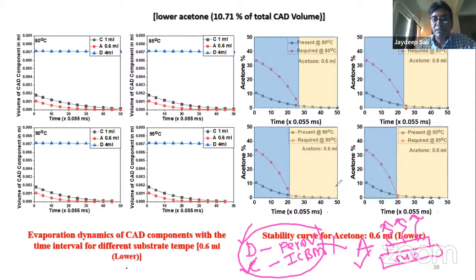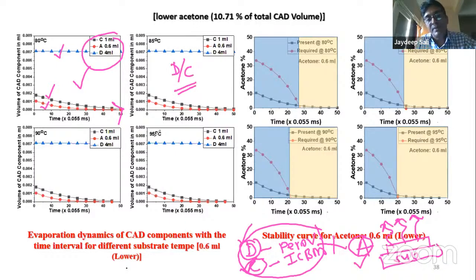So as time passes, the volume of D, the volume of C and the volume of A go on changing with time. If you focus on this diagram, you can see that the volume of the cyclohexane, the acetone and the DMSO are all changing with time as the thin liquid film evaporates to form a solid film. As the three components change, naturally the ratio of D and C goes on changing. And we have seen that the ratio D by C needs a specific volume of acetone to have microemulsion. If this acetone is not available, the microemulsion will get disturbed and it will form separate layers.